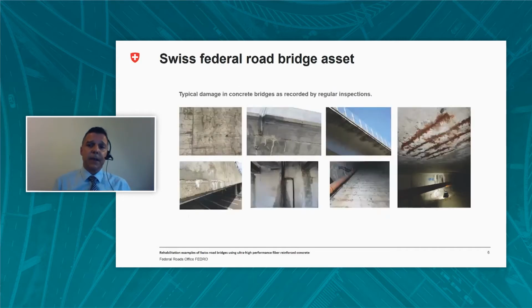However, despite the advantages that have led to the use of concrete as the main building material, the issue of durability was not thoroughly examined or taken into consideration in the past. A combination of factors such as exposure to corrosion, defective conceptual details, particularly at the abutments, presence of alkali aggregate reaction, carbonation, frost, use of de-icing solutions in the winter period, and others have resulted in some cases in important damage, which normally should not occur during the design service life of a bridge.